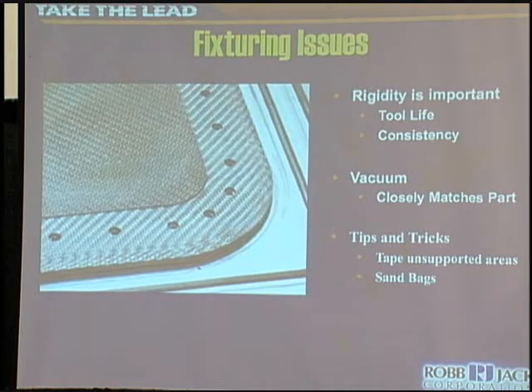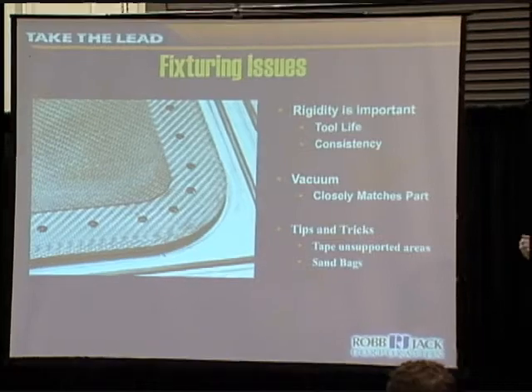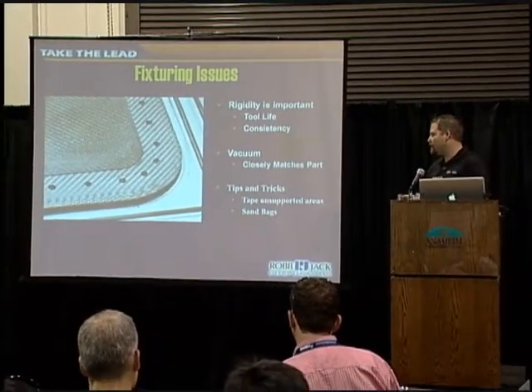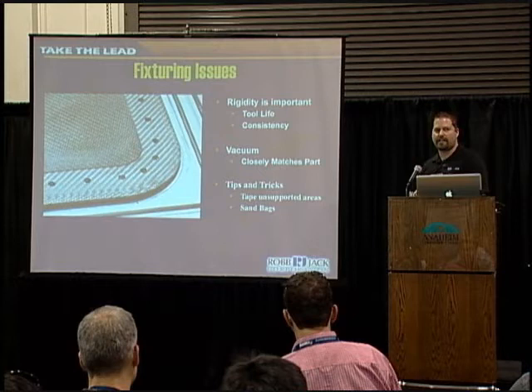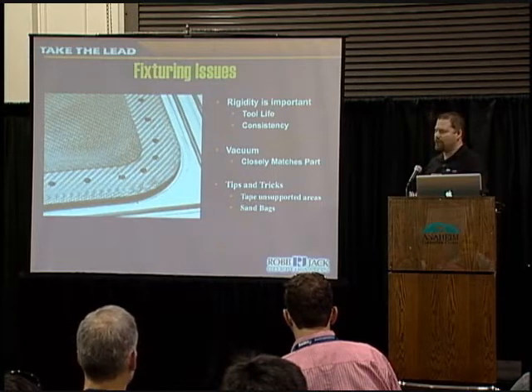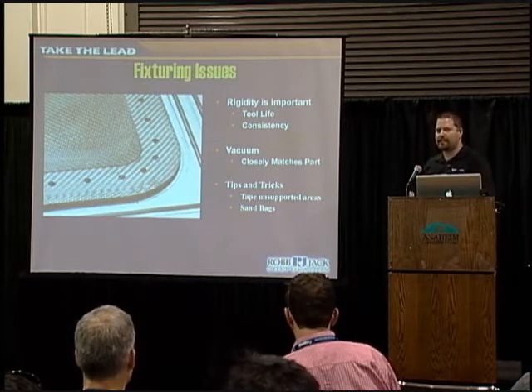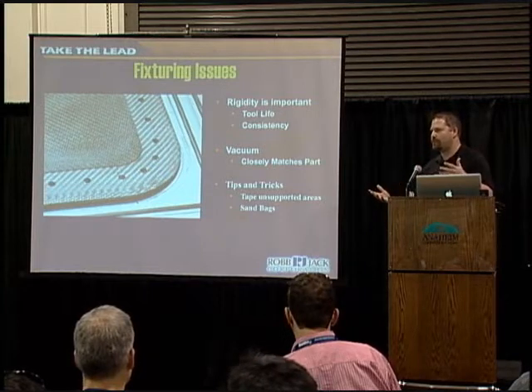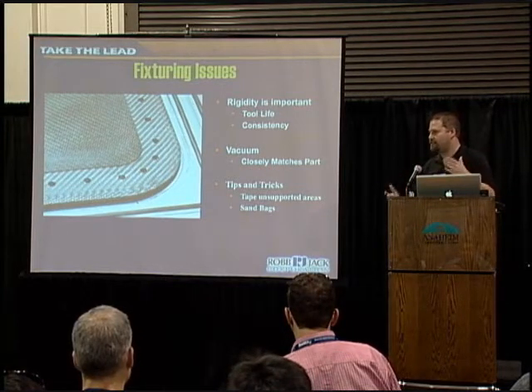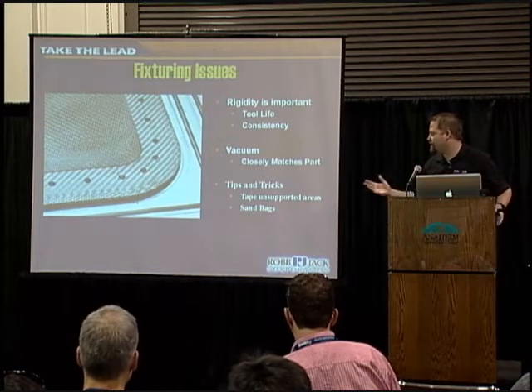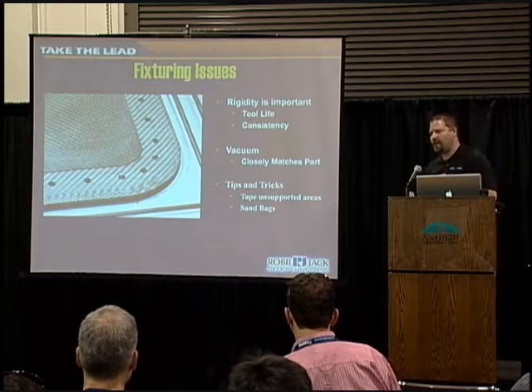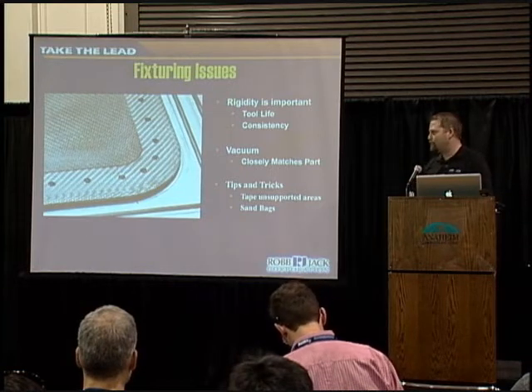And we've seen even something as simplistic as using tape on areas of a family of parts where you may only have one fixture that may vary from part to part, using duct tape or masking tape to tape the edge to the fixture. It will actually help give you that extra rigidity while you're machining. We've also seen something as simple as using sandbags to throw on top of the part to help dampen it, to keep it from vibrating. So anything you can do to make it more rigid, the better you're going to have when you do the